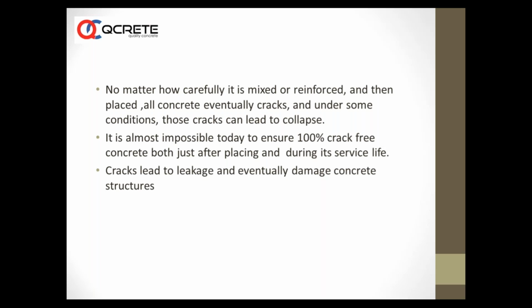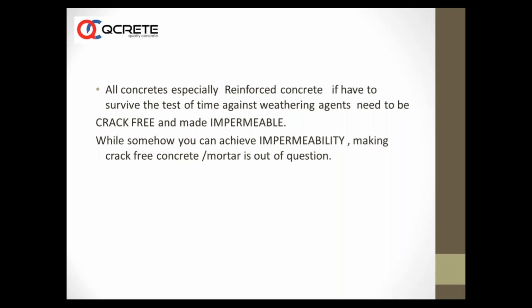Cracks will open up eventually. It is almost impossible today to ensure 100% crack-free concrete. Okay, and it costs a lot. If you want to do such kind of concrete, it costs a lot at this moment. You need to use shrinkage compensating admixture. You need to use a lot of fibers. You need to reduce water cement ratio. You need to do all sort of tricks to achieve crack-free concrete, along with a very good proper method of curing. In spite of all that, many times cracks can happen actually, which can eventually damage concrete structures. So all concrete structures, especially reinforced concretes, have to survive the test of time against weathering agents, need to be crack-free and made impermeable.